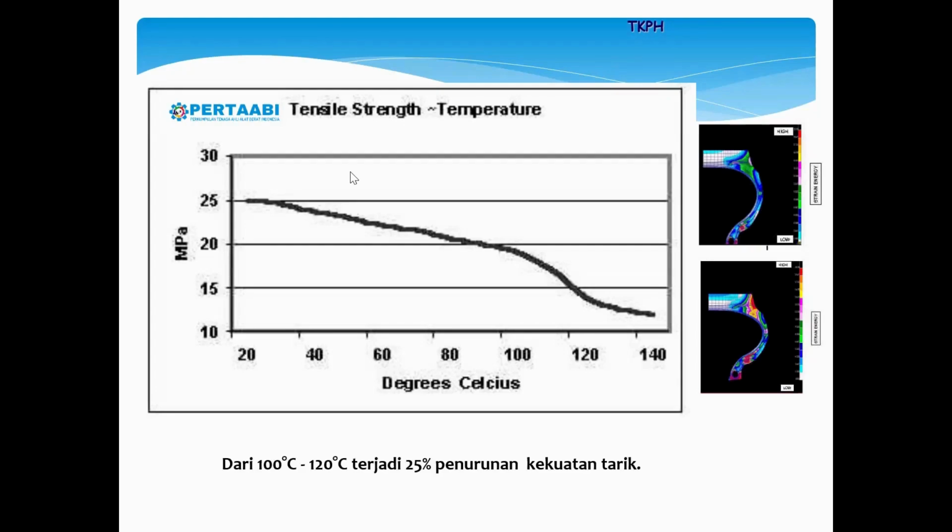And even after the vulcanization temperature, it may have lost strength. You can see that reaching 120, the tensile strength is reduced by 25%. It's never imagined, right? It's not mentioned in the guidance, even from OEM, only in SAE. But don't worry, we will adopt this into the Indonesian standard later on.